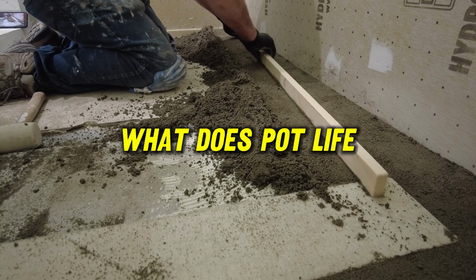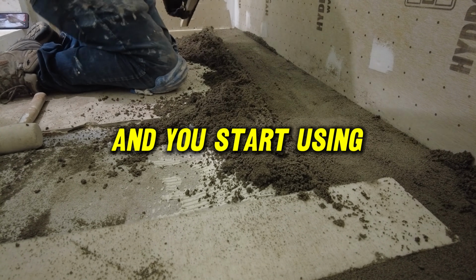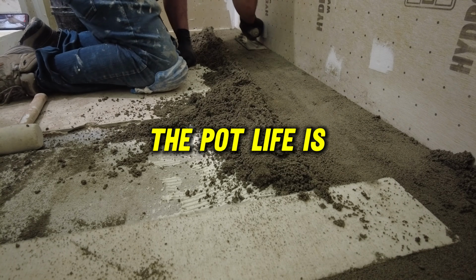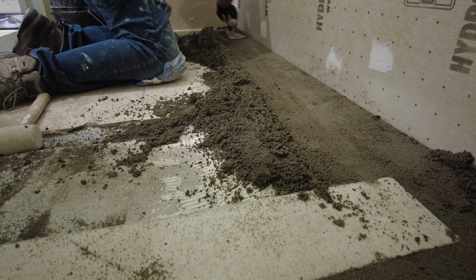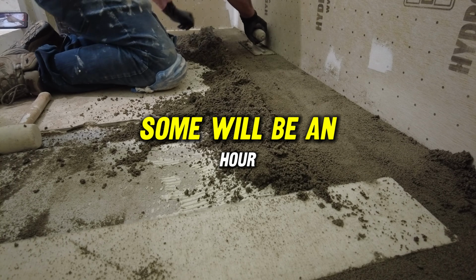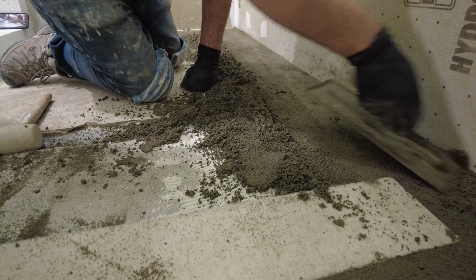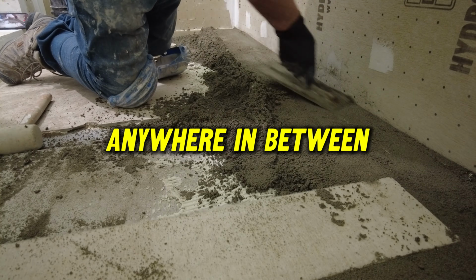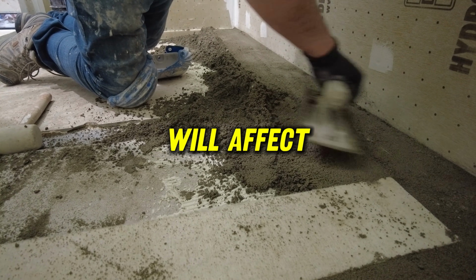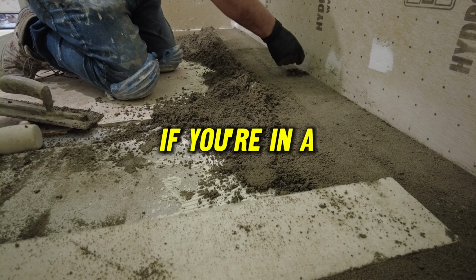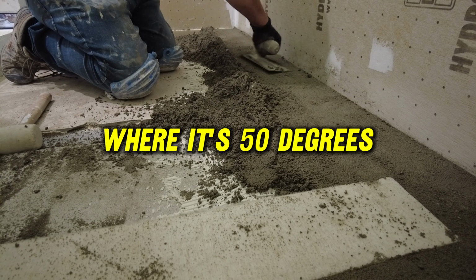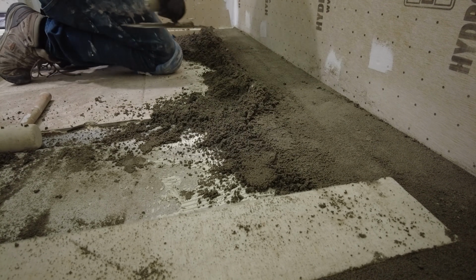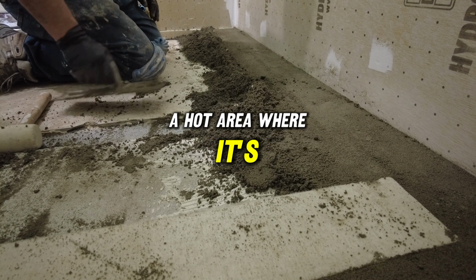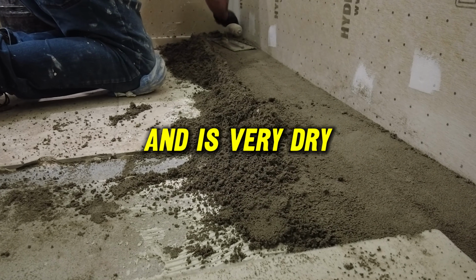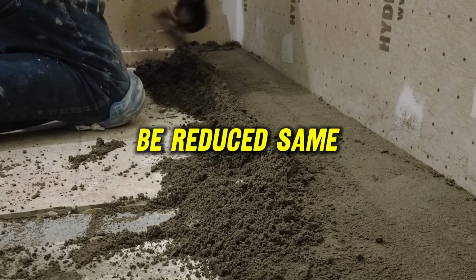So what does pot life mean? You mix up the Thinset and you start using it. The pot life is the amount of time that it will remain good in your bucket. Some will be an hour, some will be up to 4 hours of pot life, and anywhere in between. Ambient conditions and temperature will affect the pot life. So if you're working in an area where it's 50 degrees and it's damp, you're going to get a very good pot life. If you're working in a hot area where it's 100 degrees and it's very dry, pot life is going to be reduced. Same for open time.